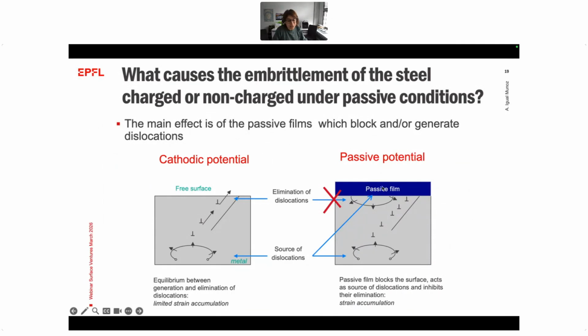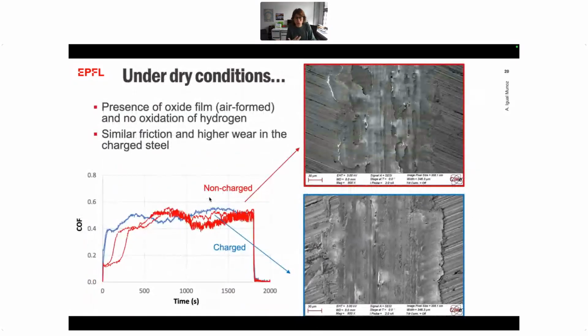So the main effect of this passive film is that they generate and block the dislocation. So we start accumulating here a lot of strain. We cannot eliminate the dislocation because we have this passive film. So the effect is an embrittlement effect. Whenever we don't have surface films, this dislocation can be annihilated on the surface, and the strain accumulation is a little bit limited. So this is the explanation why we have the same response in the case of charged and non-charged samples.